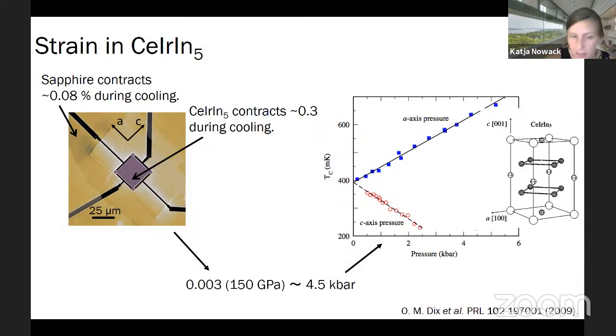And we just compare numbers. The order of magnitude of the thermal contraction is about 0.2 to 0.3%. If we take the elastic modulus, we can translate that to a pressure scale, and that comes out to be a few kilobars. If we look here, a few kilobars of pressure shifts the Tc by a few hundred millikelvin, which is consistent with the kind of modulations in Tc that we see throughout the device.